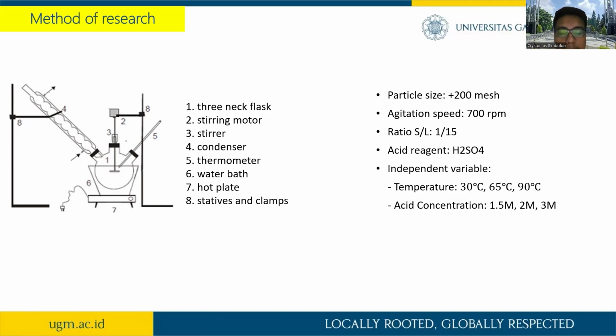The red mud sample that has been prepared will be put into a 3-neck flask that has been prepared in accordance with the series of leaching equipment. The leaching process is carried out according to the variable variation that has been determined, with the parameters of solid-liquid ratio, temperature, and reagent concentration. The leaching process was carried out for 60 minutes for all variable variation.